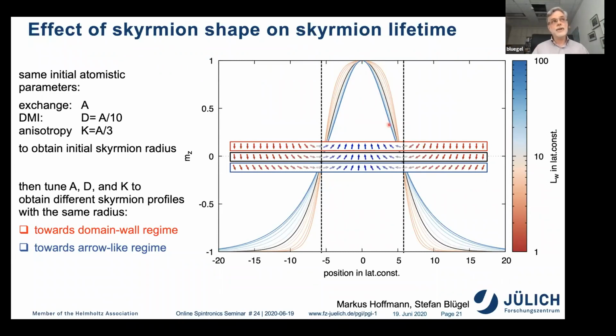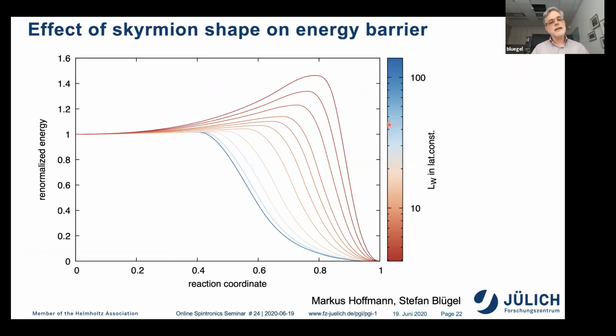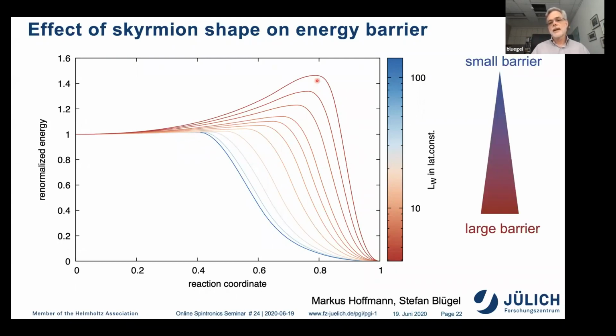And this has an influence on the lifetime of the Skyrmion. So here is the renormalized energy profile from the energy of a metastable Skyrmion over to the ferromagnetic state here. And what you see here is the barrier height varies enormously with the Skyrmion profile. So if the domain wall width is small and your kappa is small, then the barrier is high. But if your kappa is large, that means the Skyrmion radius is extremely small, and your domain wall is large, then your Skyrmion is not very stable.